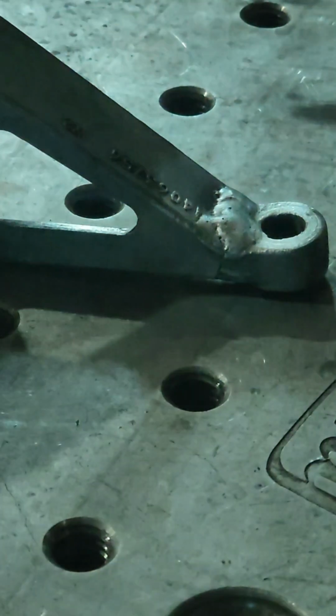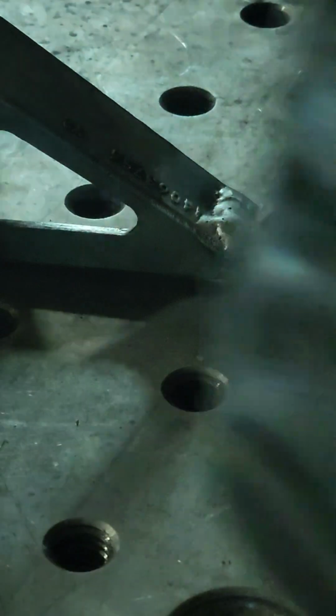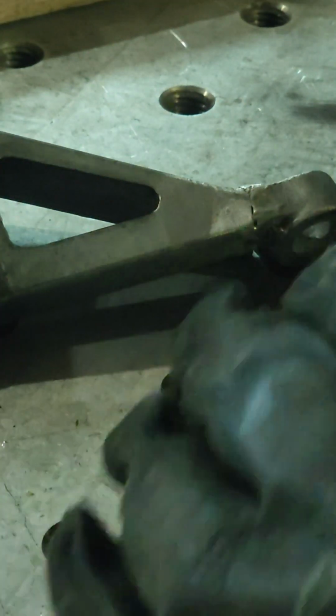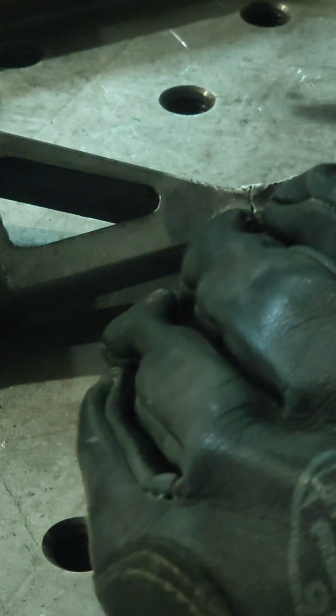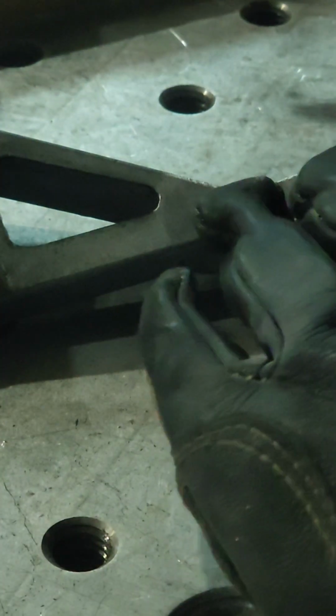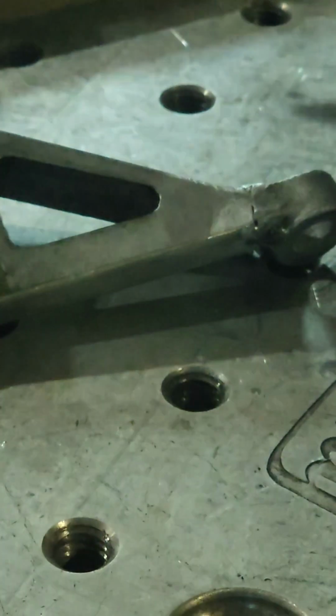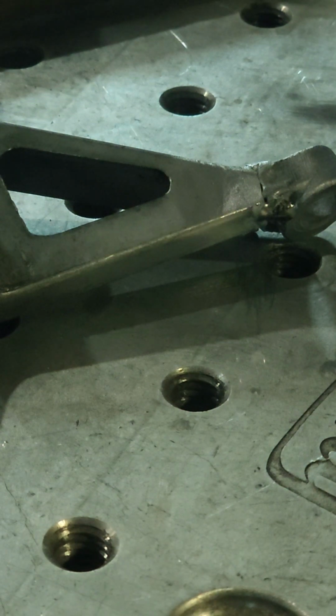If it's got a bunch of, whoa, that's hot. If it's got a bunch of holes in it, then you're going to want to go back over that. But it's looking pretty good right now. Got good penetration. Like I said, this stuff is wetting out really fast. And depending on the cast, it will. So even when you're heating it with your bottle torch, you want to be very careful that you don't overheat it. You can melt this stuff into oblivion, and then you're screwed.